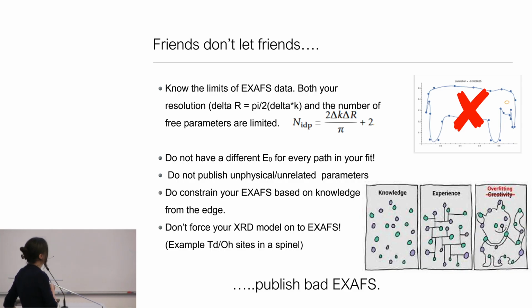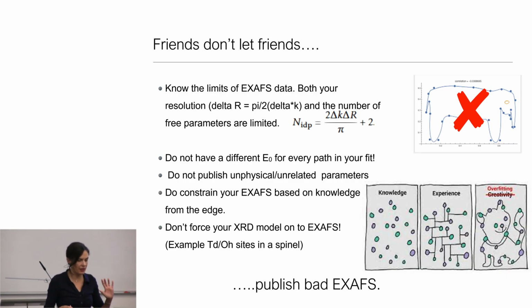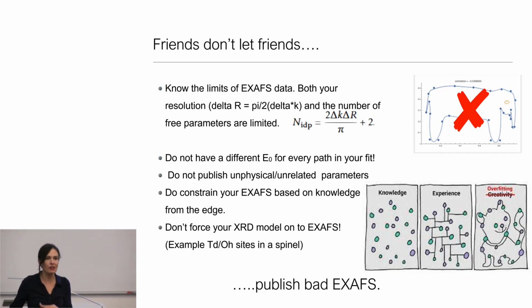The other thing is this: please don't have a different E0 for every path in your fit. This is something you see frequently, that people define the origin of the photoelectron wave vector, allow it to refine, and then it's moving by 40 eV for different paths. These things become non-physical. And because people put EXAFS fits in the SI and nobody looks at them, sometimes EXAFS gets a bad rap, and it's not fair. It has something to do with the driver, right? And this is also one of those things that one has to be aware of.